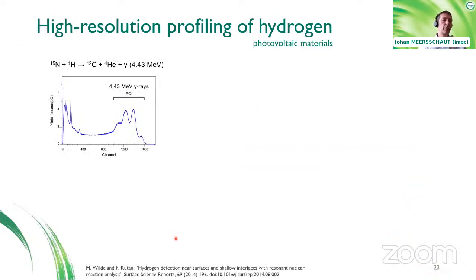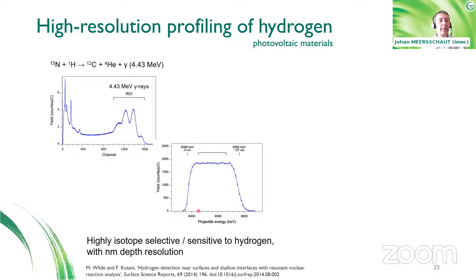One example I would like to highlight here is, again, the sensitivity to the profiling of hydrogen, for example in photovoltaic materials. So when you come in with a nitrogen-15 ion beam and you impinge it on hydrogen, you will excite gamma rays that can be very selectively measured. By tuning the energy of the projectiles, for example here you tune the energy of the nitrogen-15 ions incoming onto the sample above the 6,385 keV resonance, you can probe the amount of hydrogen in the sample very sensitively.